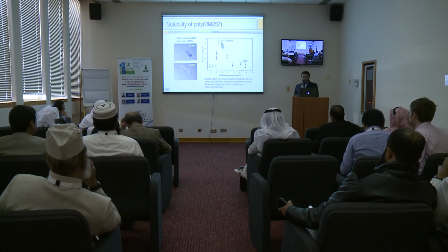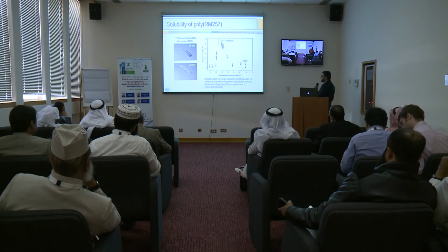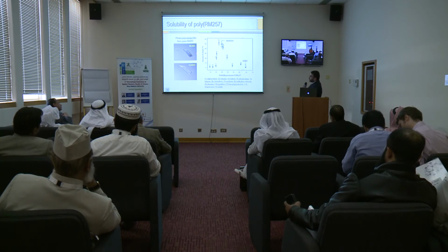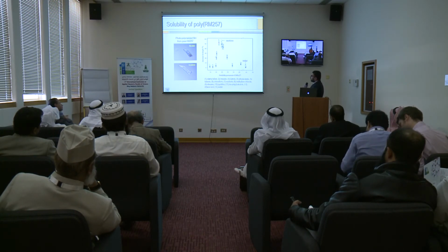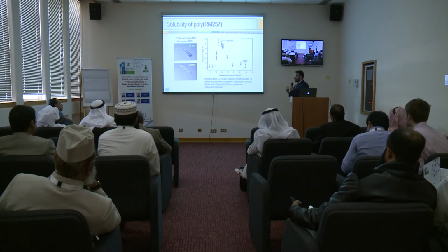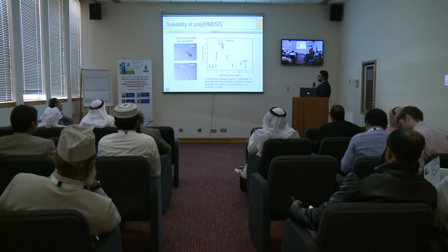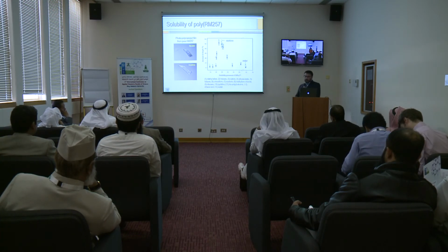So I determined the swellability of this polymer film. I used different solvents, almost 13 solvents, and swelled a small polymer piece in these solvents. I found that acetone and chloroform were the best solvents to swell this polymer a lot, and water was a non-solvent for this polymer. In further experiments, I used only acetone and water because acetone and water are miscible with each other while chloroform is not miscible with water.